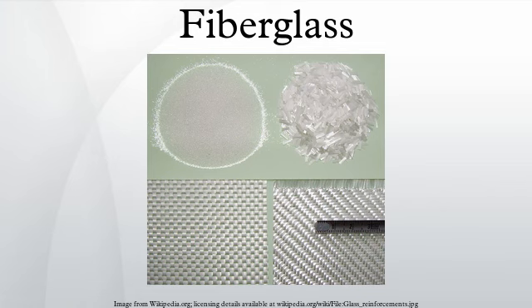Fiberglass spray layup operation. The fiberglass spray layup process is similar to the hand layup process, but differs in the application of the fiber and resin to the mold. Spray-up is an open molding composites fabrication process where resin and reinforcements are sprayed onto a mold. The resin and glass may be applied separately or simultaneously chopped in a combined stream from a chopper gun. Workers roll out the spray-up to compact the laminate. Wood, foam or other core material may then be added, and a secondary spray-up layer embeds the core between the laminates. The part is then cured, cooled and removed from the reusable mold.